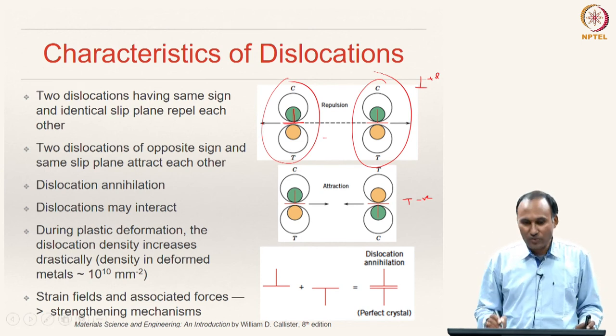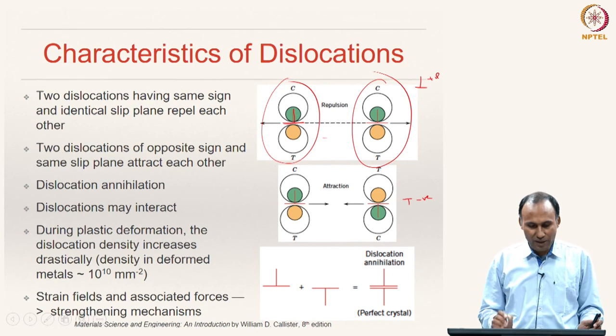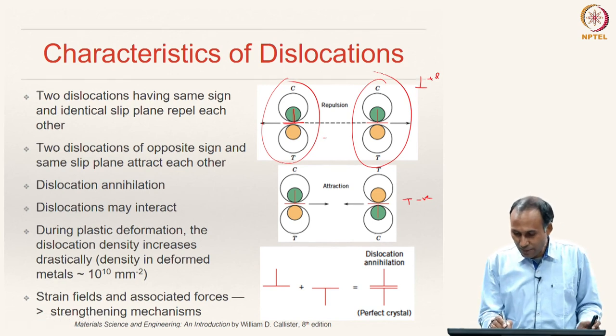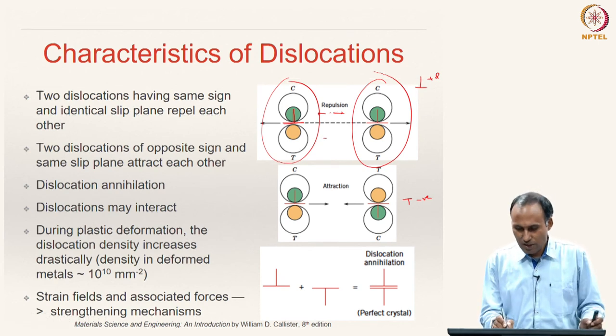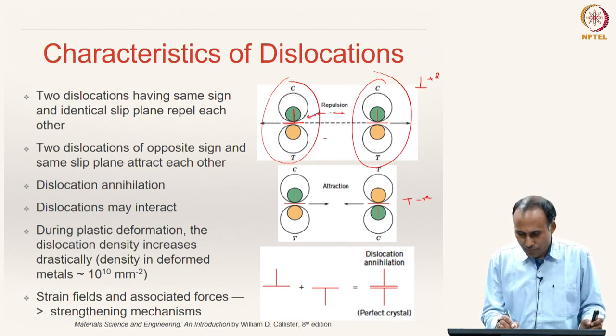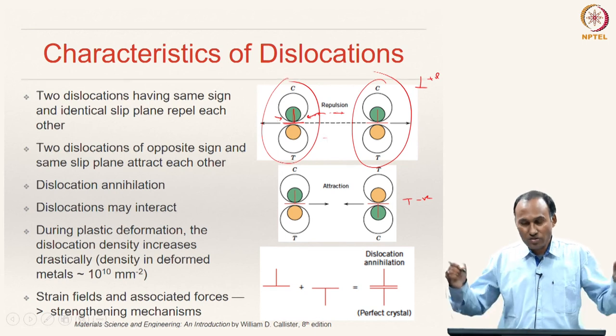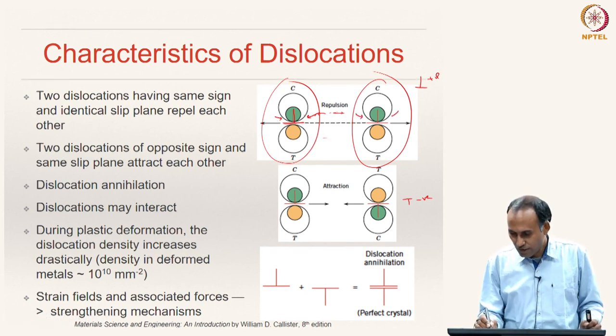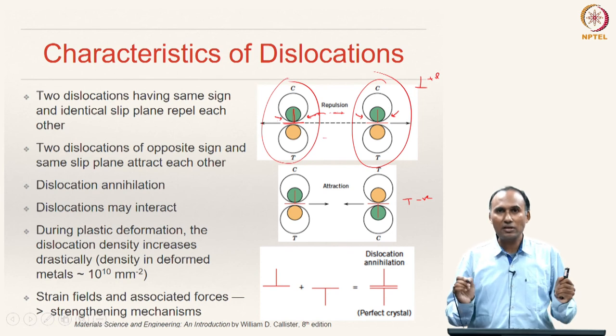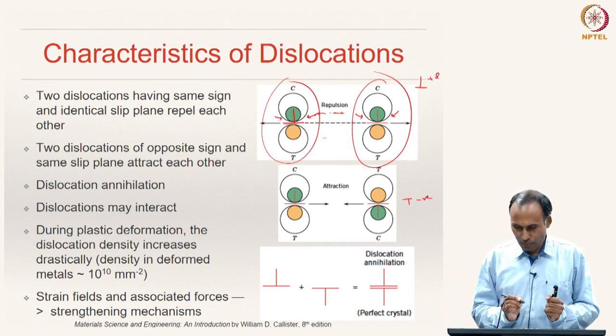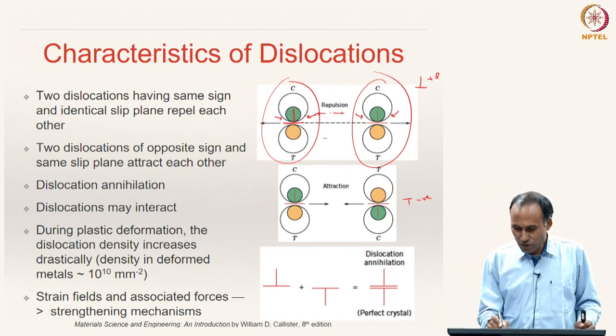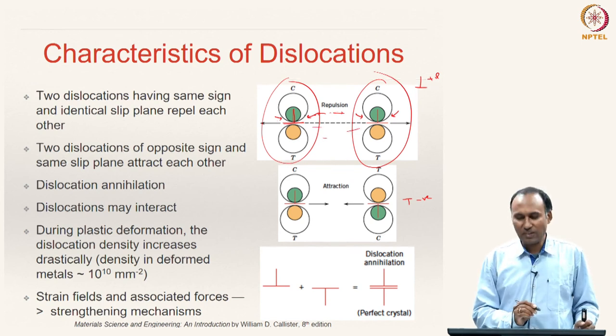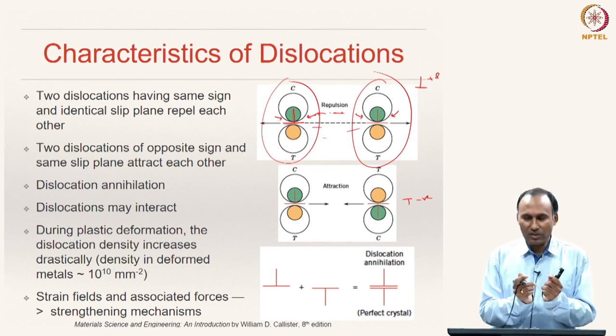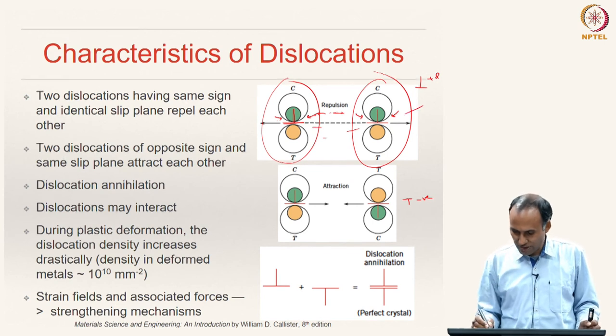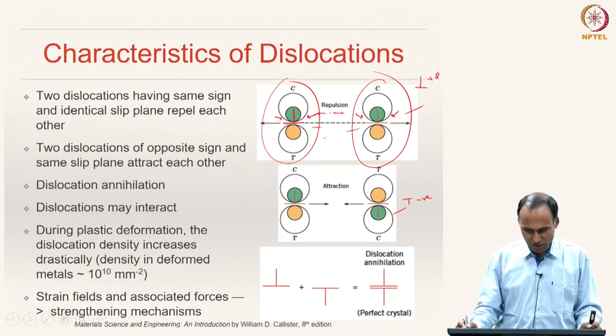If you have the same sign of dislocations in the identical slip plane, then when they come close to each other, they try to repel each other, because the atom planes are squeezed together, and this will also have a squeezing kind of stress strain field. As a result, when these two of the same sign are coming together, they repel each other, either positive edge dislocation or negative edge dislocation.